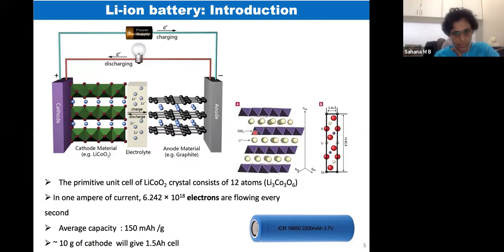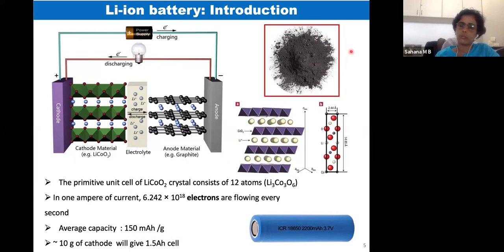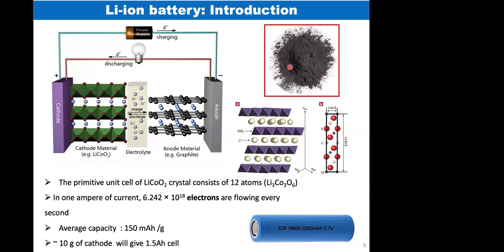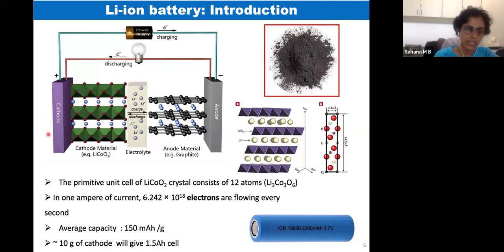So now this is 1 unit cell. This will look like these powders. Okay, this is an example of a powder of a cathode material. Similarly, we will have the anode powder, and now these powders have to be connected to the current collector. We cannot just stick a powder onto the current collector. So we need binders. Also, all these cathode materials known today, be they layered oxides like lithium cobalt oxide, lithium manganese oxide, lithium nickel oxide, or their derivatives, or lithium ferrous phosphate, are all like semiconductors. Their conductivity is not very good.